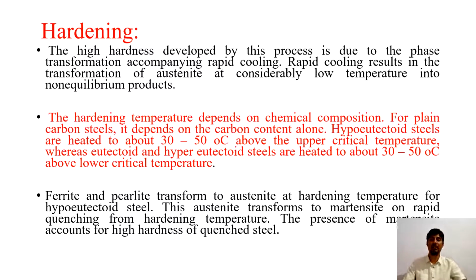The hardening temperature depends on chemical composition. For plain carbon steel, it depends on carbon content alone. Hypoeutectoid steels are heated to about 30 to 50 degrees centigrade above the upper critical temperature, whereas eutectoid and hypereutectoid steels are heated to about 30 to 50 degrees centigrade above lower critical temperature. Very important point, very important line. Please read it 2 to 3 times if you are not getting it.